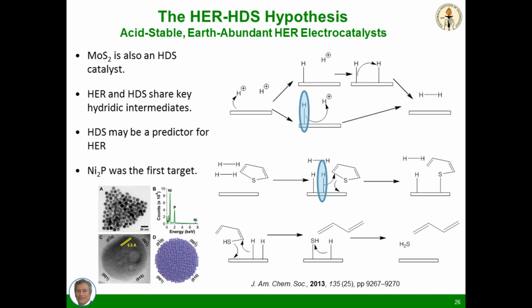Now that species, the surface-bound metal hydride that dissociates and then reforms hydrogen, is exactly the species that we believe will be the viable mechanistic route to reduce water at low temperature. Now there's no guarantee that the mechanisms and materials that work at high temperature for hydrodesulfurization will be good catalysts for low temperature hydrogen evolution, but we made a good educated guess that this would be a place that we would look. We collaborated with a synthetic nanomaterials chemist at Penn State, Raymond Schaak, and his group made these nanomaterials,